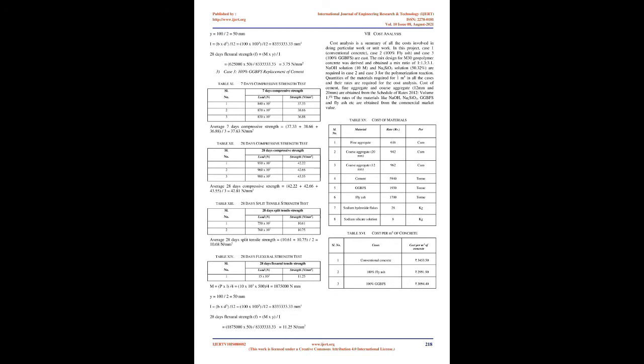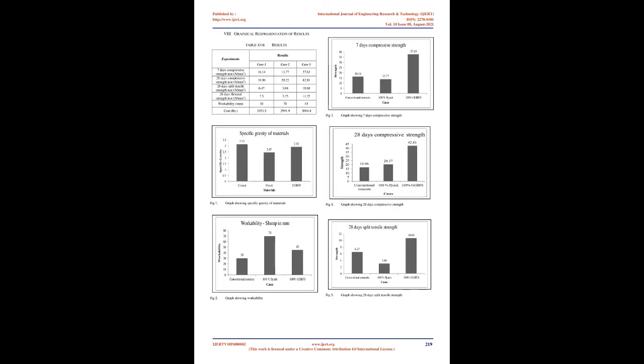Preparation of geopolymer concrete mixes. The preparation of geopolymer concrete is similar to that of cement concrete. Two types of coarse aggregates, 12 mm and 20 mm, fine sand, and source material, fly ash, GGBFS, micro-silica, were mixed in the dry state. Then add the prepared mixture solution of sodium hydroxide and sodium silicate along with extra water based on water to geopolymer binder ratio and mix thoroughly for 3-4 minutes to give a homogeneous mix.